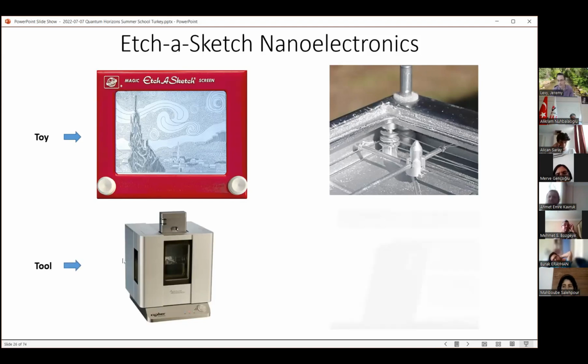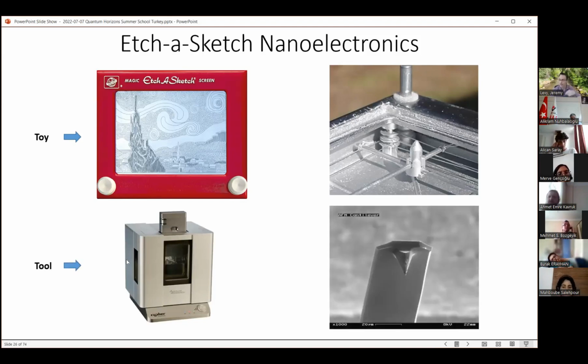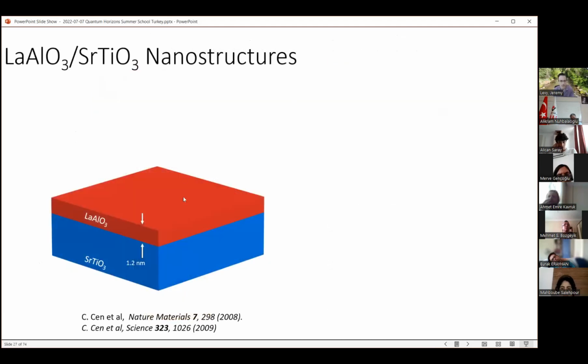We use an atomic force microscope that has a very sharp conductive AFM tip. And so the features that we create are a trillion times smaller in area than the Etch-a-Sketch. The description of how this works is that we work with this critical thickness of 3 unit cells of the lanthanum aluminate, and then we first make contact to the interface and put metal there, because this red region is highly insulating. So we need to punch through into the potentially conductive area.